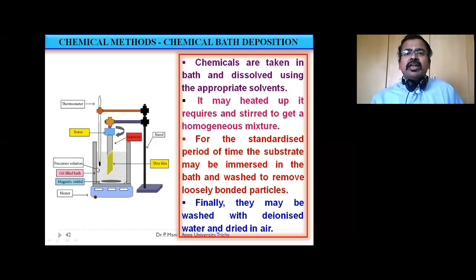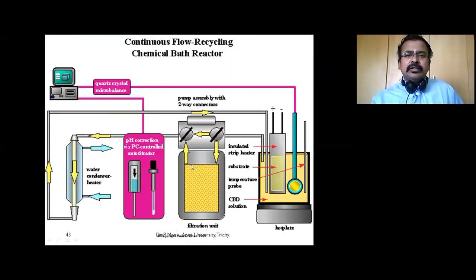Here, chemicals are taken in a bath and dissolved using appropriate solvents. It may be heated if required, and stirred to get a homogeneous mixture. For a standardized period of time, the substrate may be immersed in the bath and washed to remove loosely bonded particles. Finally, it may be washed with deionized water and dried in air. It's a simple method, and we are seeing a chemical bath reactor.